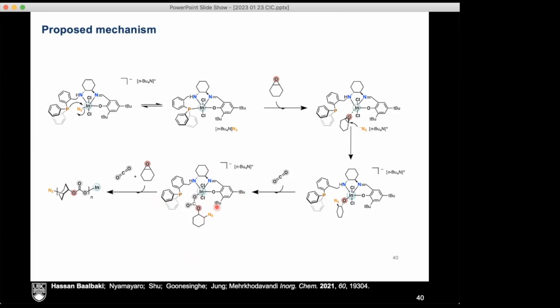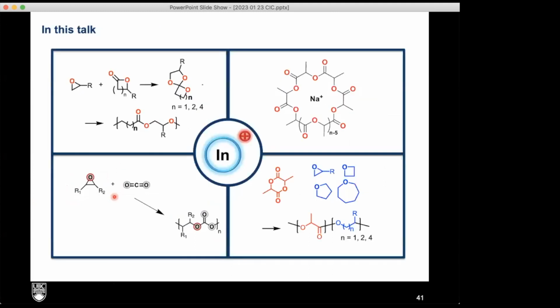And clearly in this case, we don't get an intramolecular reaction. We get an intermolecular reaction, and there is the polymer formation at the end. We definitely need to improve on this system, though, because I think that the molecular weights that we're getting are not there. There's clearly chain termination in this case, so we need to understand that. But I think this was very cool in terms of the metal reactivity.